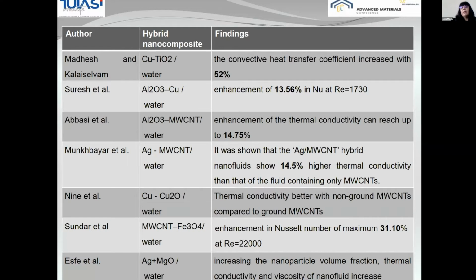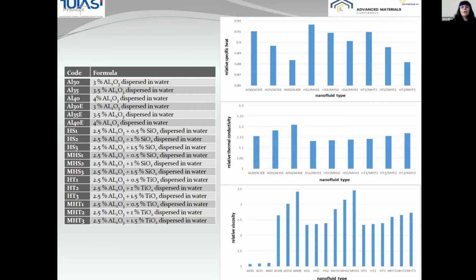Nevertheless, the use of hybrid nanocomposite was better, and some authors found an increase in convective heat transfer up to 52%. So this is rather good. But the fabrication of the hybrid nanocomposite is a little bit expensive. Our research, just an outline, found that the relative specific heat is decreasing a little bit, depending of course on the composition of each nanofluid. The thermal conductivity is getting higher by almost 22%, and the minimum increase was around 12 to 13%.